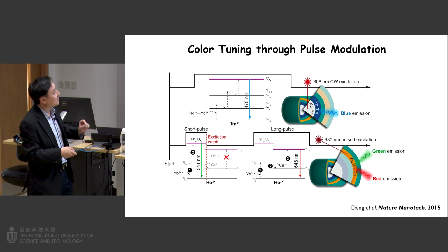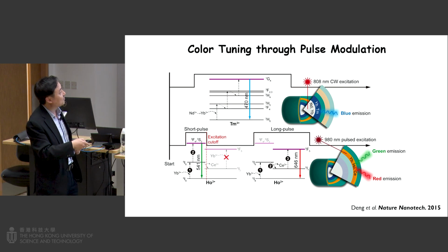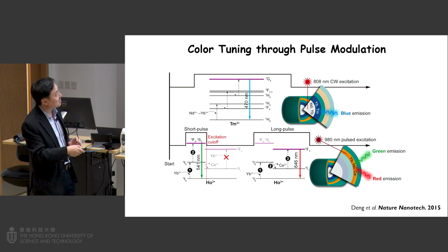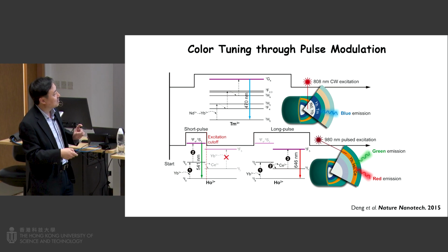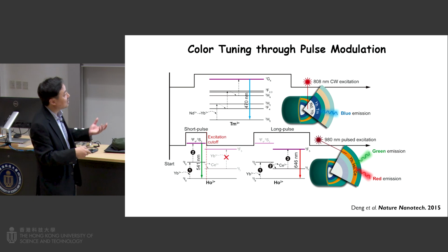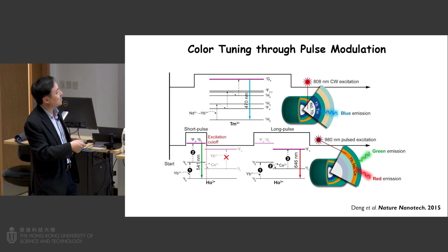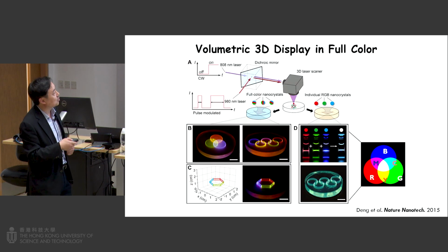Looks very complicated, but let me summarize what we learned from this material. It turns out that under 808 nanometer excitation, the blue emission actually comes from the Tm. On 980 nanometer excitation, the red emission is actually controlled by using the Ce ions. So you can see the emissions come from different processes. One is 2-photon emission, the other is 3-photon emission. So using the Ce ion, we really can control the energy transfer pathways to achieve this color tuning.